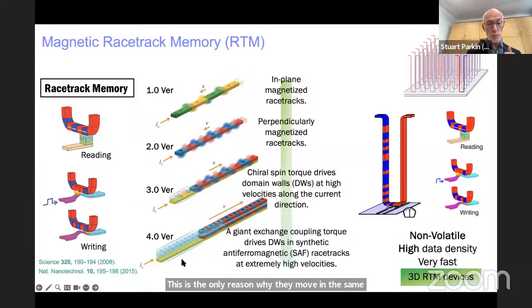Finally, in version 4.0, which is the most interesting one, we demonstrated that in a synthetic antiferromagnetic racetrack, there is another torque that moves the domain walls even more efficiently. We called it an exchange or giant exchange coupling torque. And this is a result of forming this structure, which consists of 2 racetracks, 2 copies, one on top of each other, which are coupled through an ultra-thin layer shown here as this gray layer of typically ruthenium, it could be something else, which gives rise to a strong antiferromagnetic coupling.